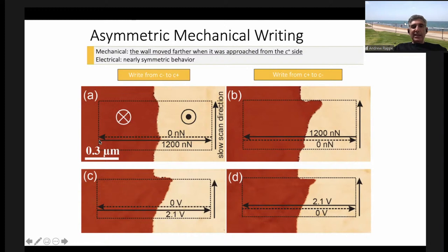Okay, now they take a tip. So this is that kind of atomic force microscope tip, and push it down pretty hard into the surface over here on the left. And then pushing hard, see they're using 1200 nanonewtons, they drag the tip to the right. Then when they get here, they lift it up so it's not touching the surface. They come back to the right. They put the tip down again and they drag to the right. Then they lift up the tip and move back to the left and drag to the right. Do you understand that experiment? And that makes the wall between the up and down domains move. You can see there's some changes here.